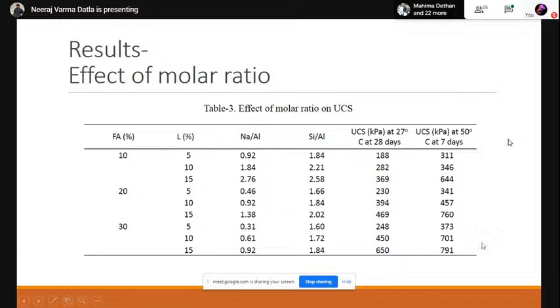And here, with respect to the peak values, we are getting the peak values for sodium by alumina ratio around 1, and for silica by alumina ratio it should be greater than 2 or in and around 2. So these are well satisfied with the literature work.